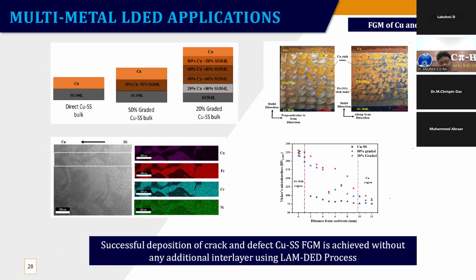Whenever we talk of laser direct energy deposition, one of the things that normally comes to our mind is, can we make multi-material functionally graded materials? Some studies were tried out by us in this direction. We did the deposition of copper directly on the SS. Then we also mixed 50% of copper and SS, and this was deposited. Then we also did the grading with 20% change, and all three samples were built, and then their properties were investigated.